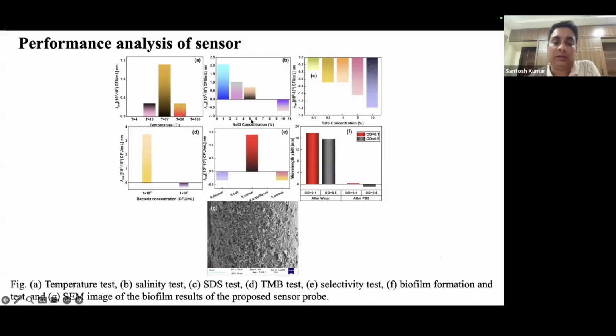And we have also done several kinds of analysis like NaCl solution and SDS concentration, and most importantly we have done the selectivity test. So in the selectivity test we have taken several other bacteria like S. flexneri, E. coli, and Shigella sonnei, and we are getting the maximum wavelength shift with Shigella sonnei bacteria, not with the other bacteria, so we can say that this sensor is specific for Shigella sonnei, because we have used the Shigella sonnei antibody, which reacts only with Shigella sonnei, not with the other bacteria.